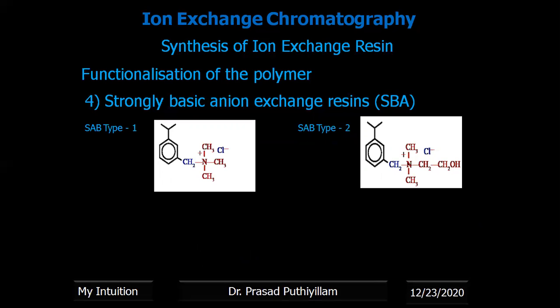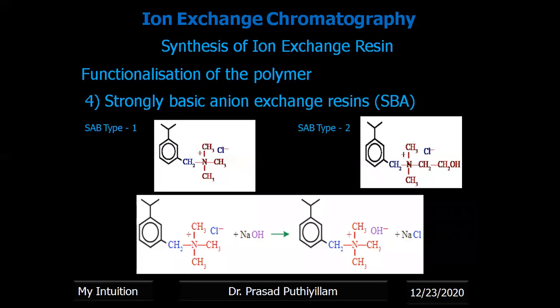It should be noted that chloromethyl methyl ether used in the chloromethylation step is a hazardous chemical, so one should be very careful while handling it. The CH2Cl form is converted into the corresponding amine form; it is stored in the quaternary ammonium (Cl⁻) form. For regeneration, Cl⁻ is replaced with OH⁻ using caustic soda (NaOH), converting it to the hydroxide form ready for application.